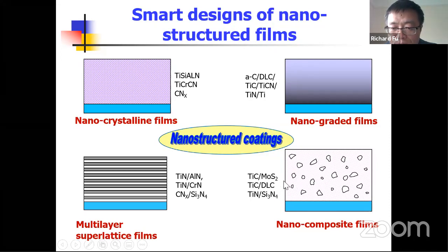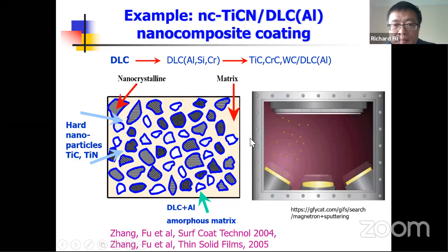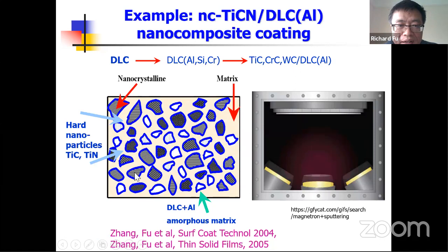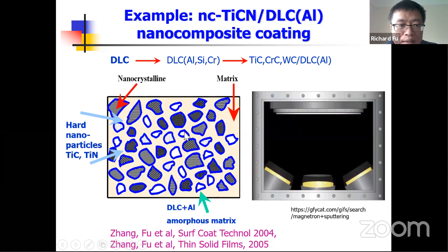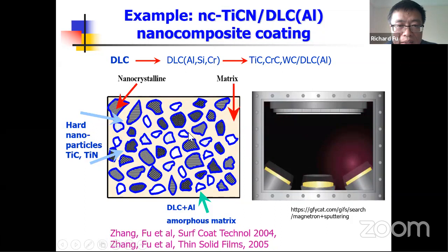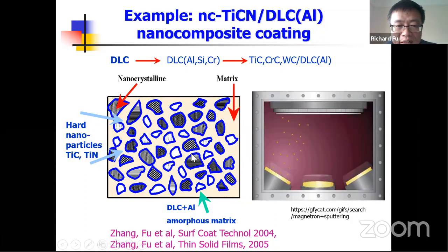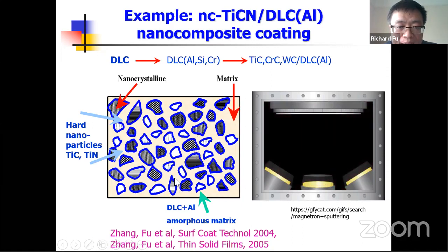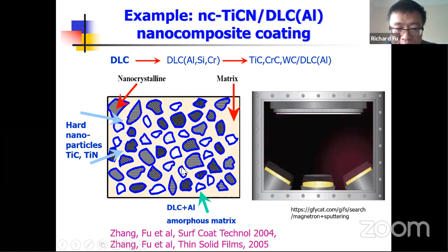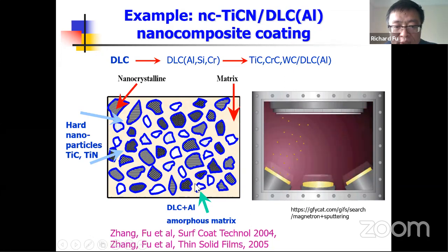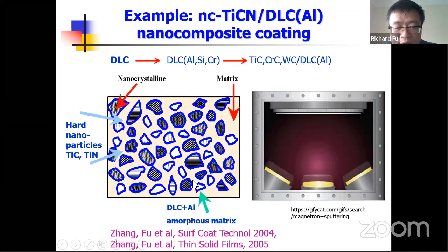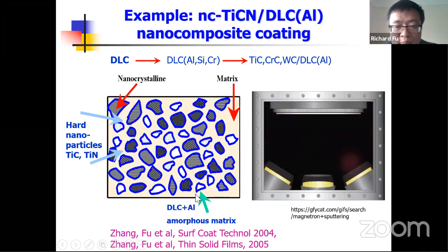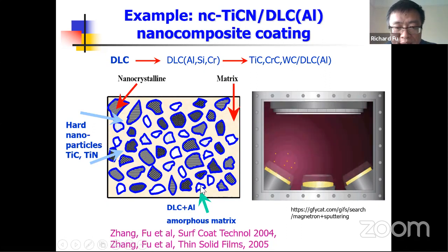So I will use one example, a nanocomposite idea, to illustrate how we can design it. Basically, here is an illustration of how we can design a nanocomposite coating which can have hardness as hard as near to diamond. The idea is that within a very tough matrix, for example diamond-like carbon or sometimes silicon nitride as a very tough substrate, we dope with elements, for example silicon or aluminum, to make the substrate matrix much tougher.